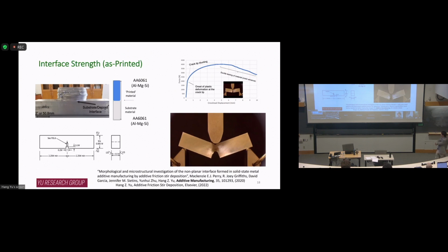As you can see, the crack barely propagates along the center or the interface. Instead, we have a large plastic zone developed around that. This is a sign of significant plastic deformation. So my interface is pretty strong. But I have to say I don't have a valid K1C measurement, because my plastic zone is large compared to my beam dimension.